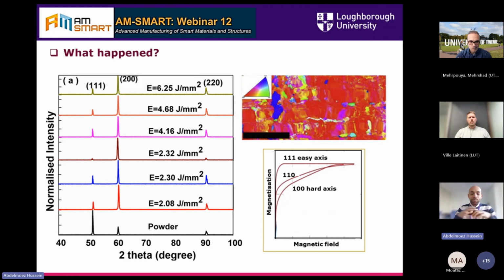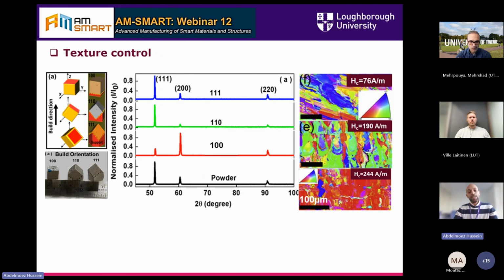So the solution for this one, we try to make a control for the texture. We try to get the texture back to the easy axis of magnetization, and to see, can we manage to do this? So we try to tilt the texture by tilting the cube by 35 and 45 degrees, as we can see here with respect to the build direction. And when we have done XRD, we find that the 111 direction starts to grow again, and that has also been confirmed by the EBSD.